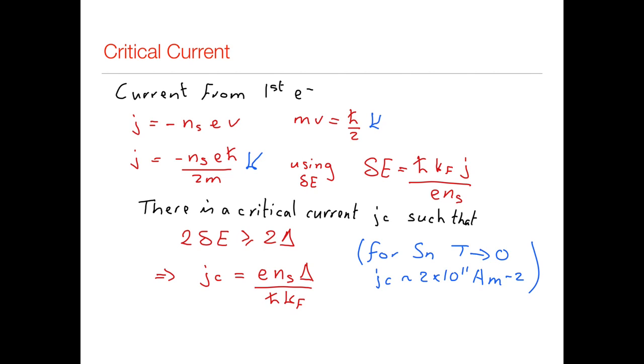Now, of course, the fact that we've shown that there's a critical current also means there's a critical field. So that was one of the very early things that we did three lectures ago. We talked about that there was a critical field beyond which we destroy the superconductivity. Why is that the case? Well, if we've applied a magnetic field, we know that there'll be superconducting currents that flow around the outside of the material to remove the magnetization inside the material.